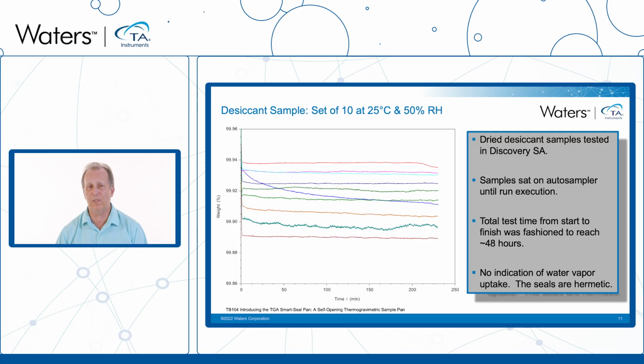So this mimics those conditions of 25 Celsius and 50% humidity, which fairly well correspond to conditions that you might see in an ambient laboratory. In fact, many ambient laboratories are going to be less than 50% relative humidity. Now, the total test time here was fashioned so as to reach a full 48 hours or 2 days. And of course, if there's any leakage through the sealed pans, you will see this as weight increasing upwards because the sample is absorbing moisture. There is no indication of that for any of these 10 here. The seals here are hermetic.